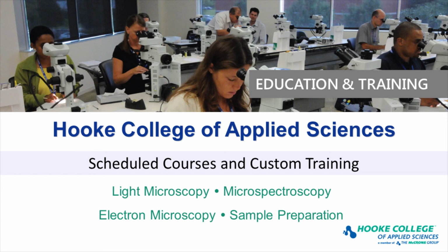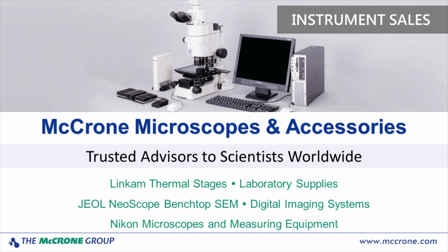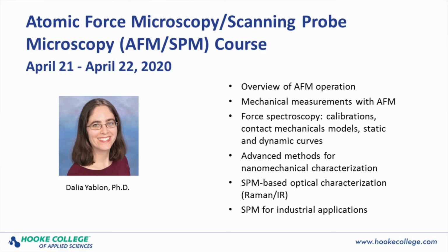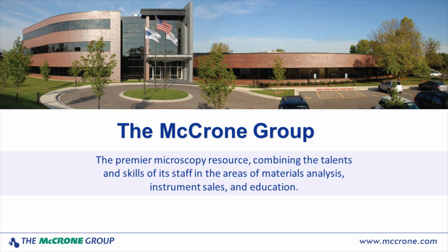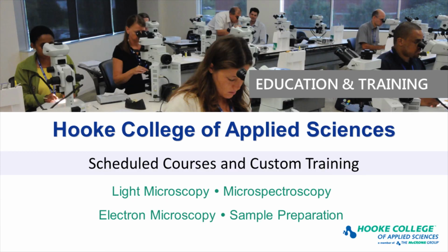You can do them either in the traditional way, which is a thermal method, or you can now buy cantilevers that are pre-calibrated by laser Doppler vibrometry. The optical sensitivity calibration is done the way it's always been done, which is a force curve on a stiff sample like sapphire. But the technique doesn't require any tip shape calibrations, which is always the concern for these nanomechanical measurements. In addition to the spring constant and sensitivity, it does have another calibration, related to the electronics and the phase of the instrument, that you have to calibrate also on a sapphire sample. That is a step that has to be done, but the classic tip shape and tip radius calibrations are not required for AFM Nano DMA.